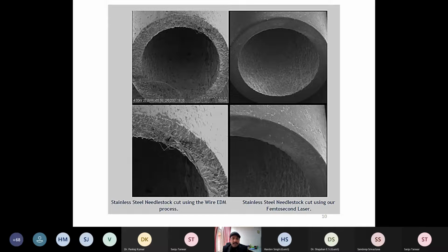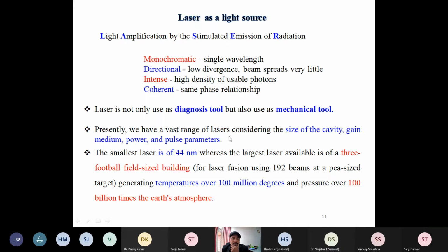So this is a comparison of some structures. This is a steel needle, and that is cut by wire EDM, electrical discharge machining, on the left-hand side. And here you see the surface is not very good, and some of the residual part you can see here. But if you cut this needle with the help of a laser, the structure is very fine and almost no residual is there. So this is the beauty of laser-based techniques.